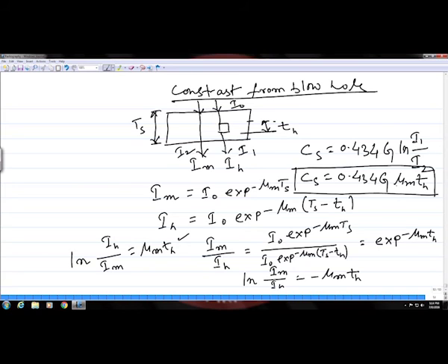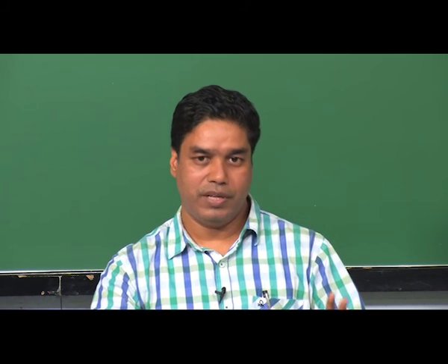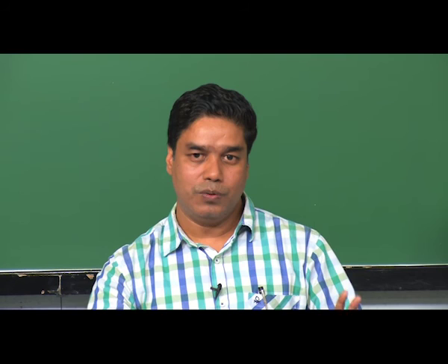And if the material is known, then the mu m is also known. So, there again you have to see whether C s is greater than or equal to 0.2 or not. So, when you get a value of C s based upon this, the blowhole will be clearly visible on the radiographic image for the parameters which are used to capture that particular image.